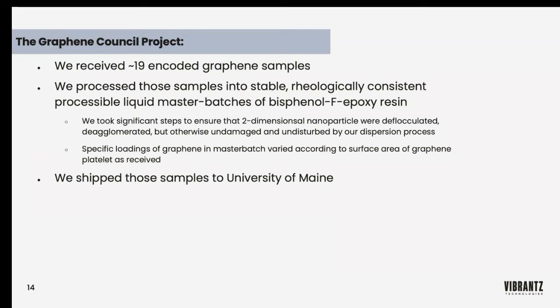Very specific loadings that we achieved varied somewhat according to the surface area of the graphene that we were working with. But basically everything was handled as close as possible to exactly the same way without introducing additives or other variables into the process that might confuse or produce noise in our results. So once that was done, we then shipped the samples to the University of Maine for further testing.